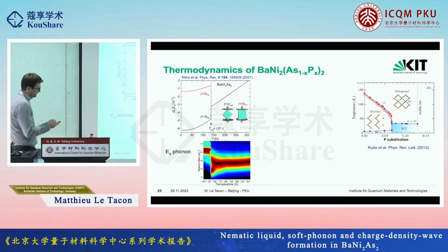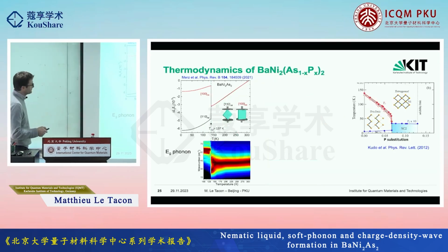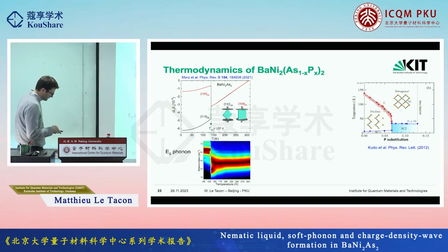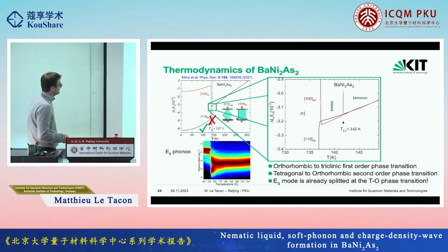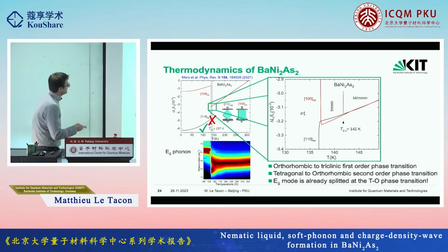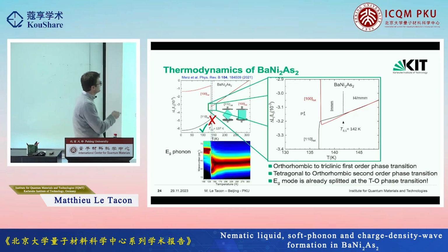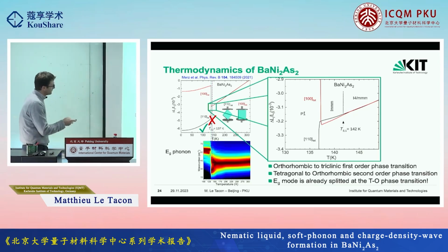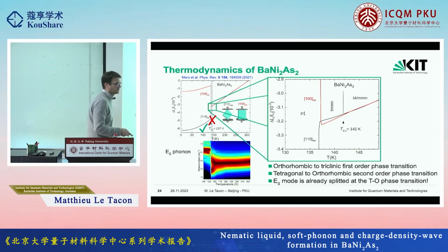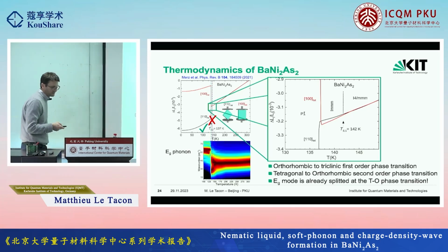So just to convince you first that what happens here is not normal. Sorry, I made this control plot. So I'm comparing here again the thermodynamic measurement with our data. So again, we can nicely see when we enter the triclinic phase, and we can also see that the effect, and I think on this contour plot this is very clear, the effect onset well above this kind of tiny orthorhombic distortion. So that's something which is very weird.